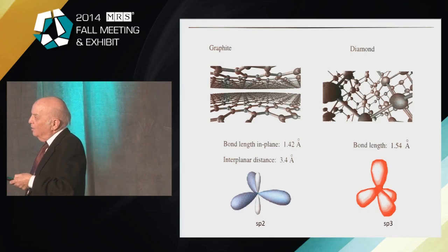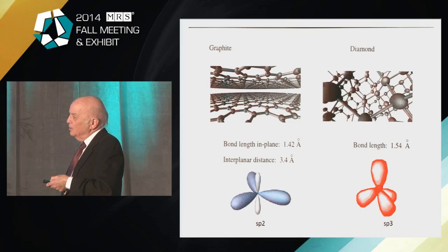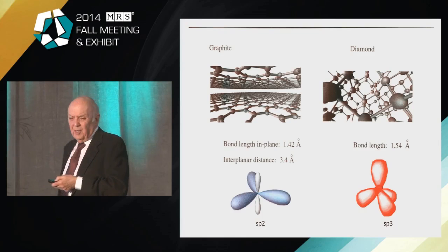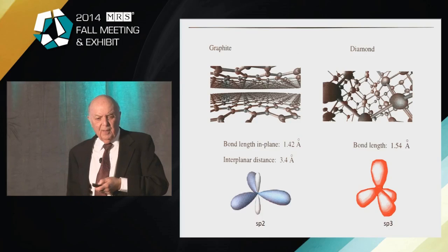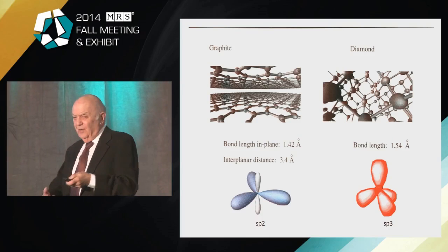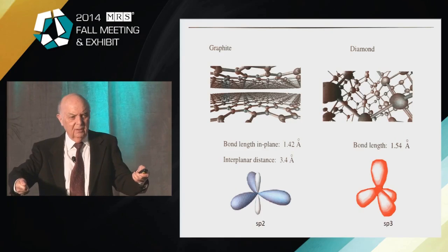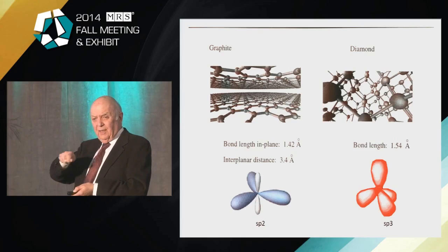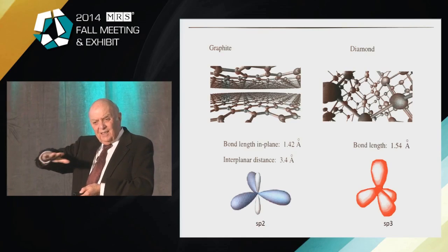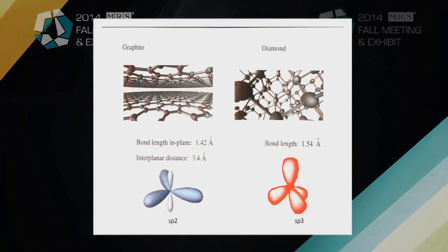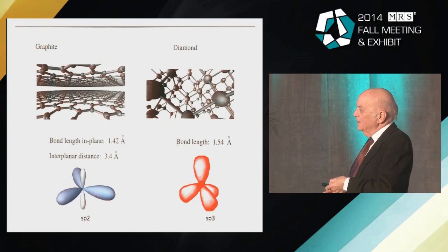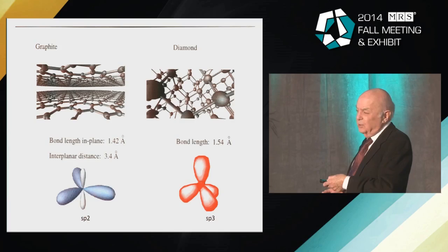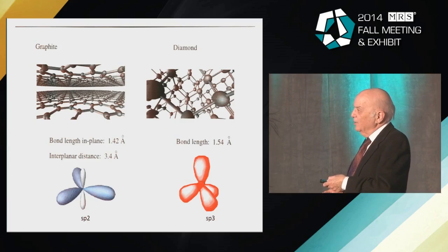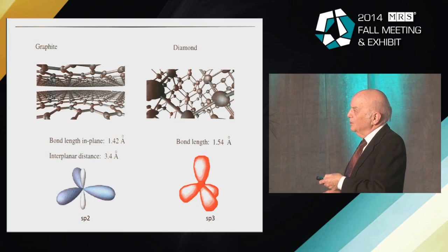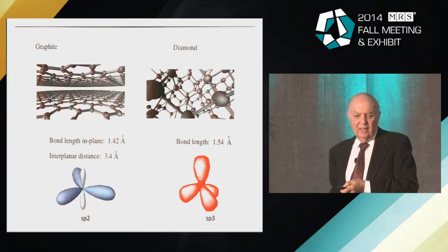So in the plane of graphite, you have these layers which are graphene, and the bonds are very short, so they're very strong. If you remember that empirical formula, it went like 1 over the 3.5 power of the bond length. So actually, if you could pull on graphene, it's stronger than diamond. However, the graphite in your pencil lead, when you run your pencil over paper, it leaves layers of graphene because the layers are separated by a wide distance, and the bonds between layers are van der Waals bonds, which are very weak, so you can pull these off. In fact, the Nobel Prize was awarded to people who were clever enough to put Scotch tape on the top of this and peel off single layers of graphene.